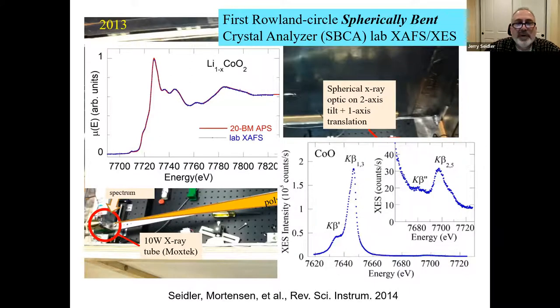So though there are some exceptions where you can do fluorescence mode in the lab, for the most part, you're doing transmission mode XAFS in the lab because your flux has difficulty getting too much above 10^6 per second. On the other hand, for emission spectroscopy, all of the photons from your X-ray tube that are above the binding energy can excite fluorescence. And that's actually quite a large core hole generation rate, 10^11 per second and above. And so you can be certainly at 1% of insertion device count rates for emission spectroscopy, which is great for anything that's more than a fraction of a monolayer, let's say.